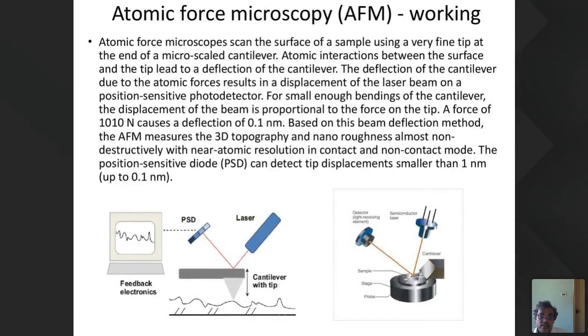Let us see the operation now. I told you about this cantilever; there will be a contact force, an atomic force, between the tip and the surface. To maintain this force, whatever the cantilever distortion is will be studied through the laser scanning. It will be detected by the position sensitive diode. The oscillation will be detected by this diode, which will be correlated to your surface feature. This is the fundamental: the deflection of the cantilever due to the atomic force results in a displacement of the laser spot on a position sensitive photodetector. The small bending of the cantilever, or displacement, will be studied and correlated.